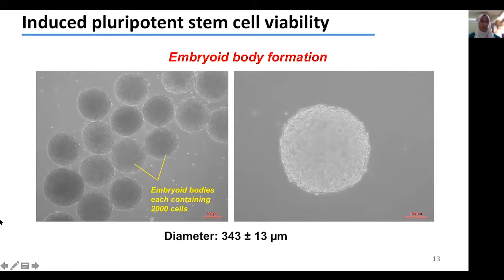We also looked at whether the scaffolds could be used to support the growth of induced pluripotent stem cells. So briefly, we fabricated embryoid bodies consisting of around 2,000 induced pluripotent stem cells. As we can see from the optical image on the right-hand side, the embryoid bodies were very uniform in shape, and the average diameter of each of those embryoid bodies was around 343 micrometers.